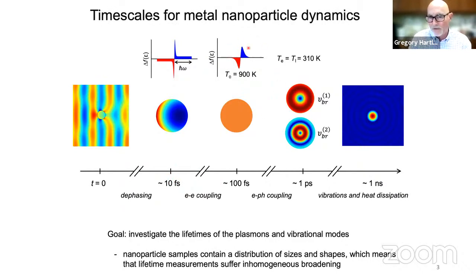Okay, you can create a very high temperature of the electrons. When you do that, the electrons now are not at equilibrium with the lattice, with the atomic motions in the particle. And so the electrons will exchange energy with the phonons. And that process, electron-phonon coupling, takes a few picoseconds. And when that's over, the electrons and the lattice are at the same temperature.